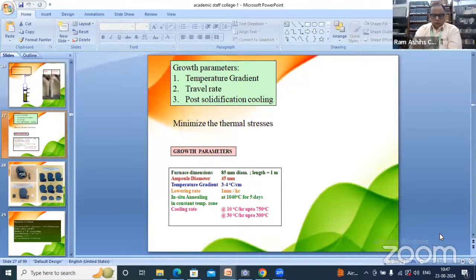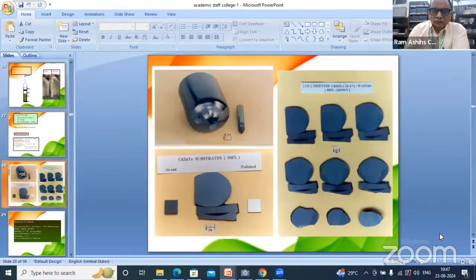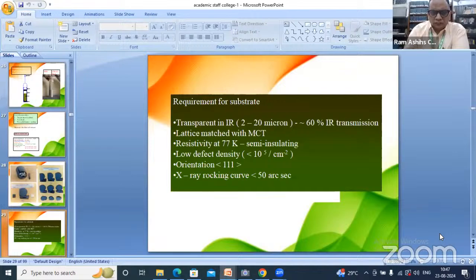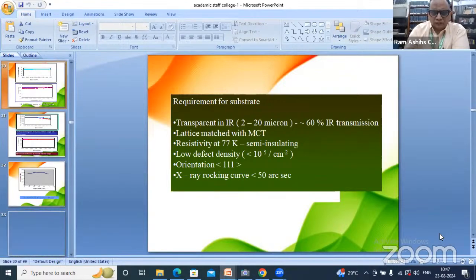After that, the furnace will be cooled at 10 degrees centigrade per hour to 750 degrees, and after that at 30 degrees centigrade per hour to 300 degrees centigrade. These are the CZT crystals. This is the requirement of substrate materials.